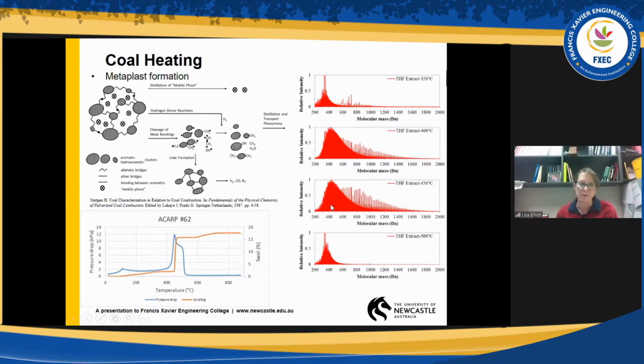So what happens when you've got this liquid phase forming? If there's enough surface tension and enough viscosity, you are going to be able to capture gas bubbles as they're being released. So if you form things like methane and other low chain hydrocarbons, they are going to be at these temperatures a gas. So as it comes off, these bubbles form and the whole structure will turn into a foam. That means because it's trapping these gas bubbles, the whole coal will swell. And that's what you can see down here on this graph. This red line shows how much swell has actually occurred. And you can see it's about 17%. This coal is a non-swelling coal. This is what we would call a thermal coal suitable only for use in a power station. It wouldn't make a good coke. Coking coals can swell 200, 300, 400 times their original size. Okay.